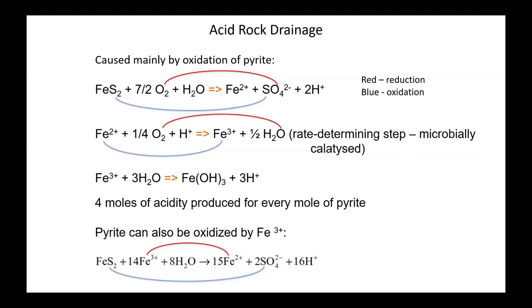Now, this step of the three reactions here can be the slowest, and it's actually microbially catalyzed. Thiobacillus ferrooxidans increases the rate of this reaction by orders of magnitude. And then finally, the Fe3+ will precipitate as ferric hydroxide. And that's not an oxidation reduction reaction, but it generates acidity. And those three reactions, when you put them together, mean 1 mole of pyrite generates 4 moles of acidity. Pyrite can also be oxidized by Fe3+, the reaction at the bottom there. So that means once the reaction starts, it doesn't necessarily need oxygen to keep it going. Next slide.